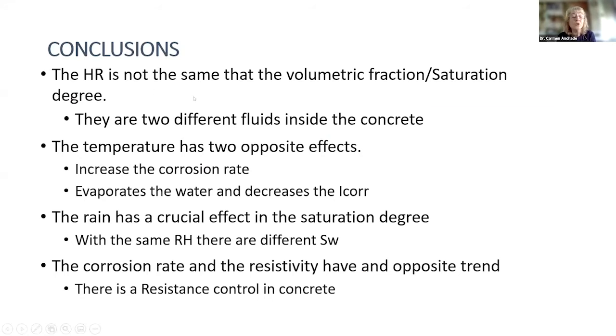And as conclusion, the relative humidity is not the same as the volumetric fraction of the saturation degree. There are two different fluids inside the concrete, and therefore the corrosion rate is not a function of the relative humidity. The temperature has two opposite effects: it increases the corrosion rate, but as it evaporates the water, it decreases the corrosion rate. And it depends on which moment and how fast the temperature changes whether you can have one or the other opposite effect.